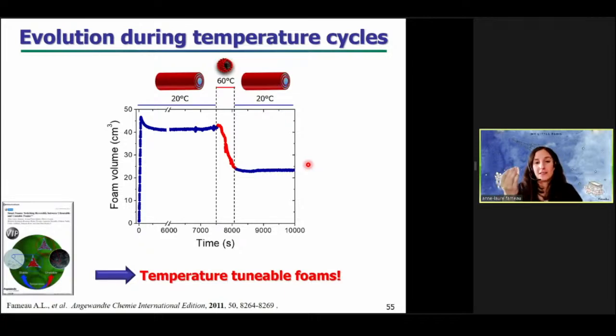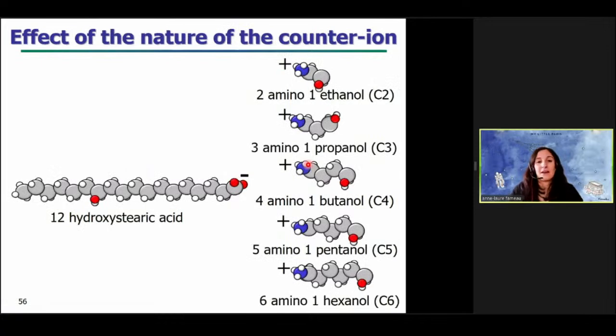The main problem with this system for real industrial application was that the temperature transition between tubes and micelles was at 60 degrees, and it was still too high for a lot of industrial applications. So then we decided to study how to tune and decrease this temperature transition to lower temperature. The first parameter that we studied was the effect of the nature of the counterion. For this, we just decreased the chain length of the counterion from 6 to 2 carbons.